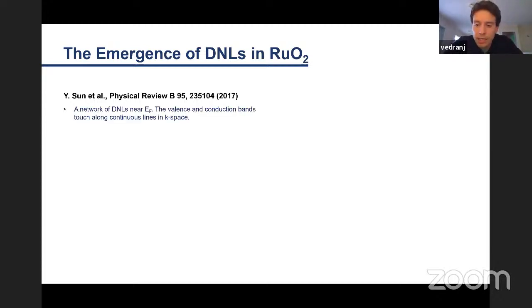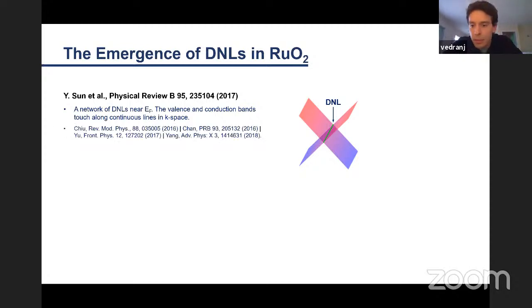So essentially it tells an experimentalist who wants to measure the band structure of this material what it looks like theoretically. It tells us that the symmetry considerations in conjunction with DFT calculations predicted what's called a network of Dirac nodal lines close to the Fermi level. And in contrast to the more prominent Dirac and Weyl semimetals, which host fourfold and twofold degenerate zero-dimensional Fermi points, the Dirac nodal lines have a one-dimensional Fermi surface.